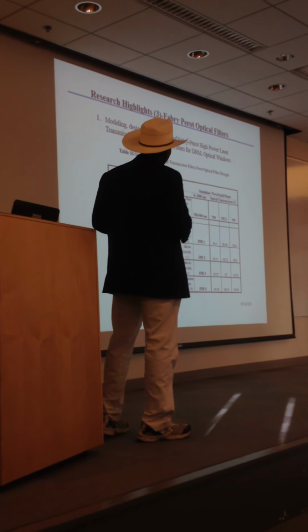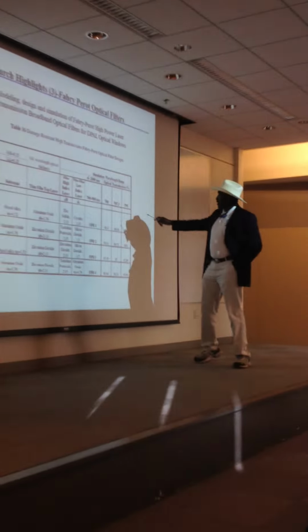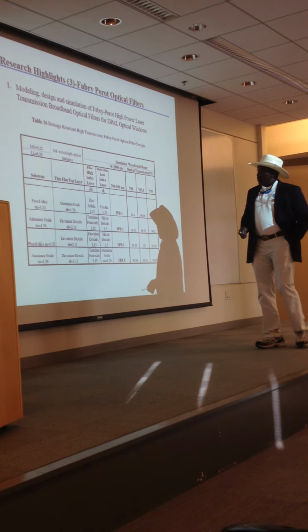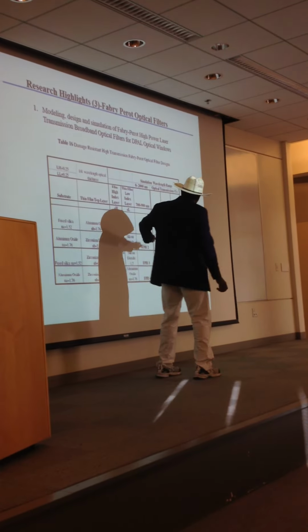And we're trying to pass a laser within the range of 700 to 900 nanometer, and with a mid-band of somewhere around 785.5. This is a low end. This is mid-band. And so we've come up with a number of different possible combinations to be able to achieve this. Again, high index, low index, reflective layer, and achieving as much as 99.49% transmission.